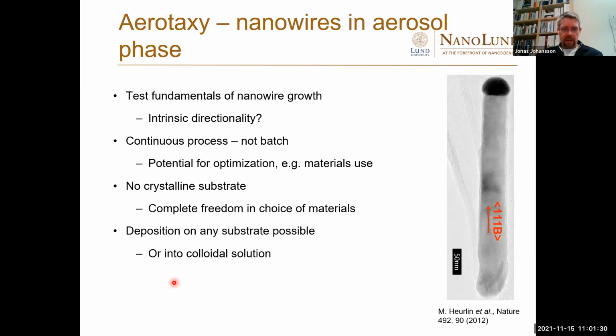And that method is known as aerotaxy. So it's a continuous process, not requiring any substrate. So there is no crystalline substrate, and we can choose materials quite free. So we can deposit on any substrate afterwards when we collect the nanowires, or we can catch them in a colloidal solution if we want that.